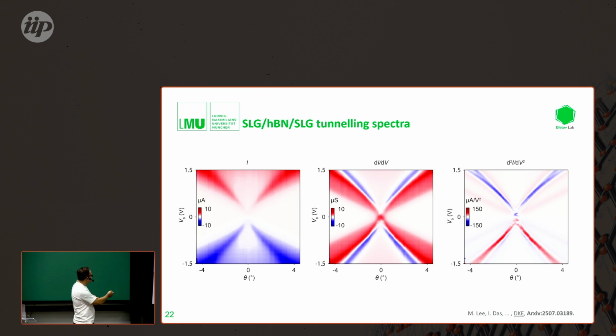And so now we can take spectroscopy data, and this is the data that we're obtaining with such a technique. Here we measure IV, dI/dV, and the second derivative of the IV. The bias voltage you can think of translating into an energy axis, and the twist angle you can think of translating into the momentum. So we are taking an energy spectrum as a function of momentum, similar to ARPES.